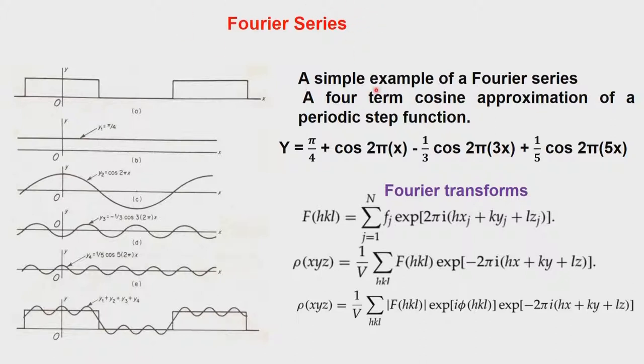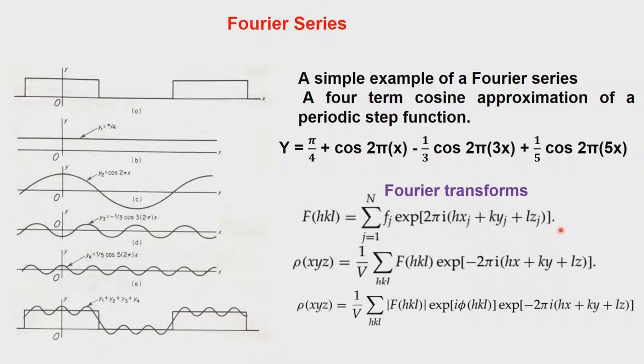In the context of the resemblance of this Fourier series to what we are doing in Fourier transforms: we have a large number of observations in terms of h, k, and l — measured from our reciprocal lattice. From the reciprocal lattice we have measured a very large number of h, k, l. What we have to fit are the values of xj, yj, zj associated with the atomic scattering factor fj. The Fourier transform of the structure factor expression gives us the electron density. So this expression should in principle represent the electron density associated with the system.